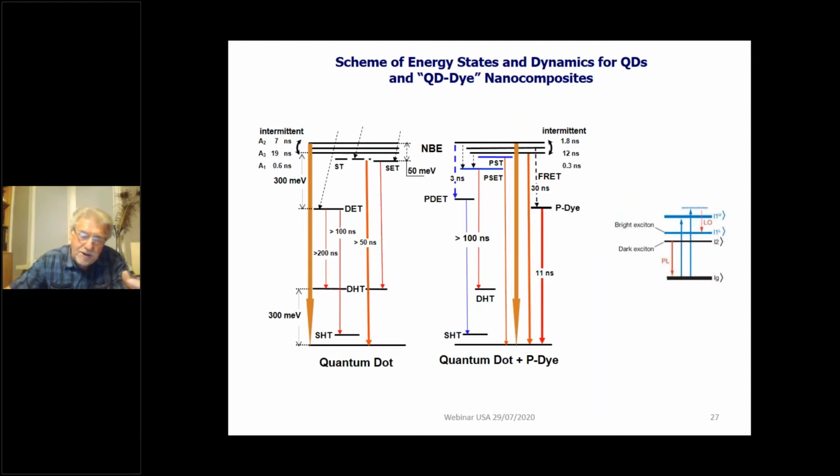The quenching is complex in this case, and energy transfer takes place, but does not play the main role in the quenching process of our systems. These results have been obtained for cadmium selenide quantum dots.